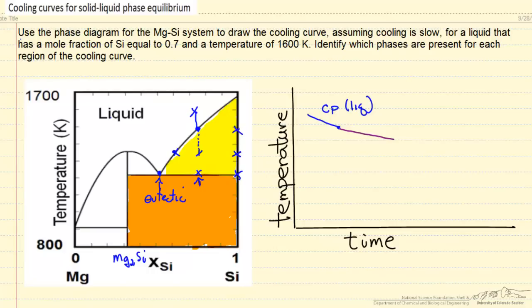On the cooling diagram, this means we're going to be at constant temperature, so this is actually horizontal. This is the formation of this compound and pure silicon in equilibrium, and the eutectic liquid disappears.